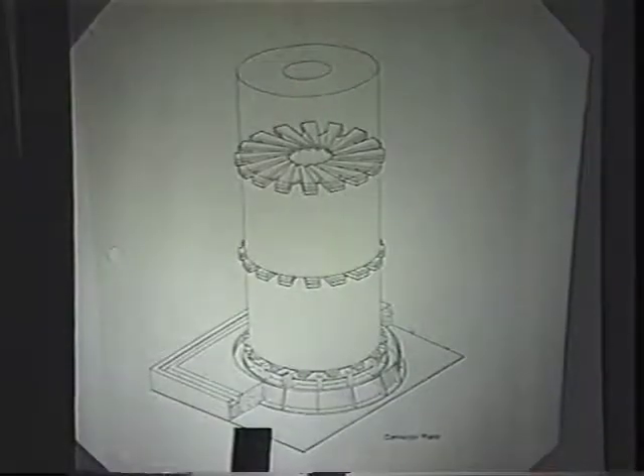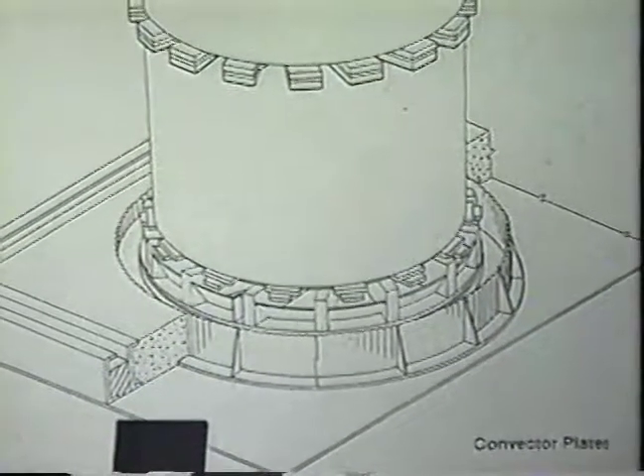Okay, the batch anneal facility. In our batch anneal facility, as I said, we take a whole coil and anneal it. But we do more than that. We take a whole bunch of coils and anneal it. Okay? This is a pictorial of an anneal stack. In our batch anneal facility, as a quick description, we have stacks of coil up to 190 inches high, 4 of those stacks in a furnace. So anywhere up to typically 9 to 12 to 16 coils in a batch anneal heat. Okay? Hence the term batch anneal. You do a whole bunch at one time. And there's some economies of scale there.